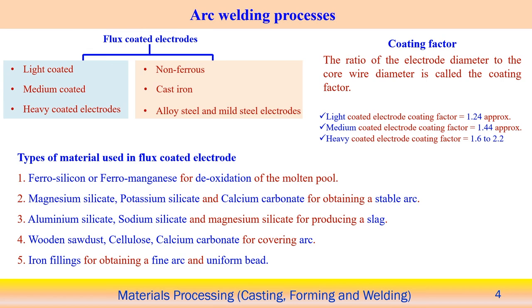But in this case, there is another factor, that is the coating factor, because what can be the thickness of the coating on the electrode? That can be decided by the ratio of the electrode diameter to the core wire diameter. So actually, the metallic wire diameter, that ratio indicates the coating factor. For the light coated electrode, the coating factor is approximately 1.24. For the medium coated electrode, it is around 1.44, and for the heavy coated electrode, it can be around 1.6 to 2.2. So these are the different coating factors you can use depending on the application.